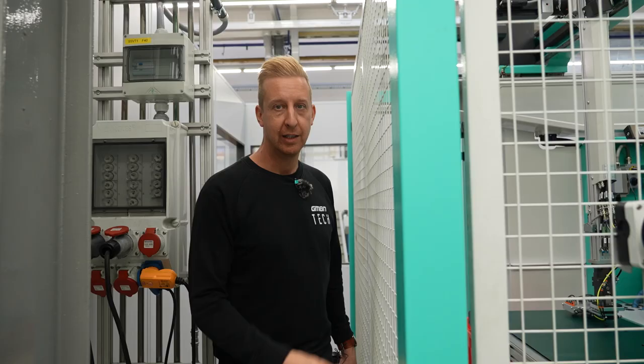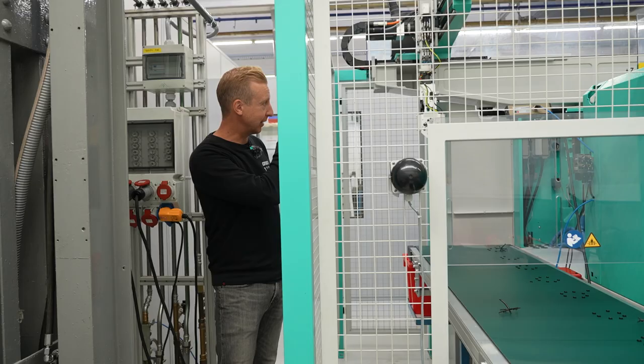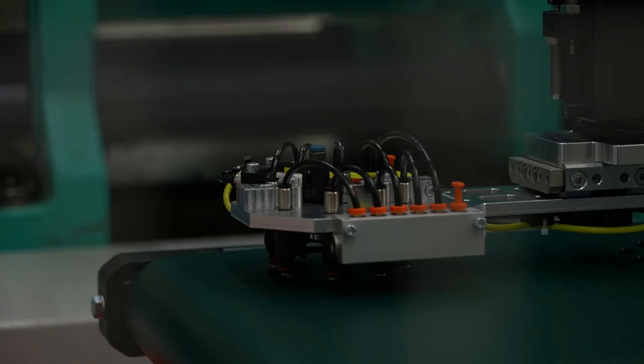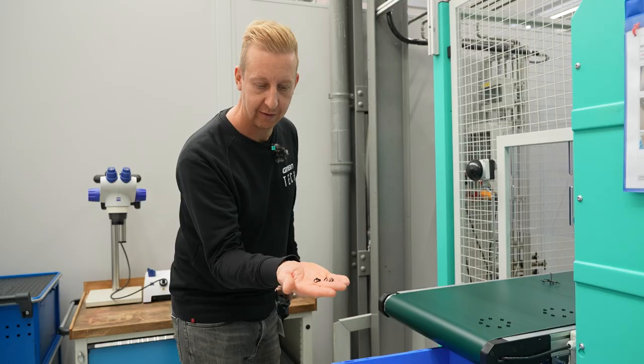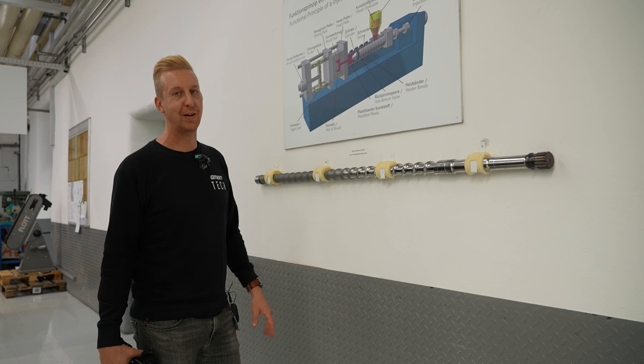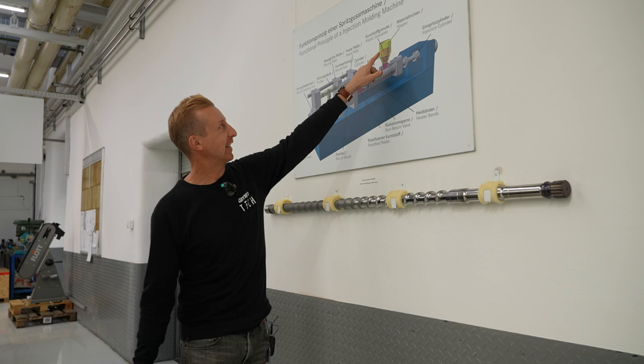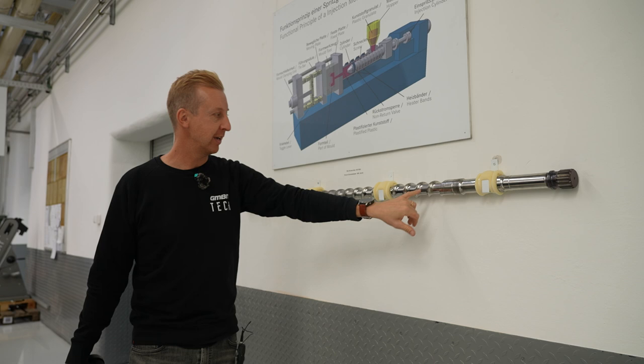Here's another injection molding machine, this time making seals. There's a tiny air jet that sprays ionized air onto the little seals — because they're so small, when they're hot they don't come off the molding machine properly, so it cools them down so they drop off perfectly onto the conveyor belt and into a little basket. Literally everything is done in-house. There's also a diagram on the wall showing the principle of an injection molding machine — you can see the granulate dropping into the hopper, down onto the screw where it's heated up. Note how the bore on the screw changes — quite coarse at the top where the material is cooler, much finer at the end as it turns to liquid, then pushed into the mold where the pressure is applied.